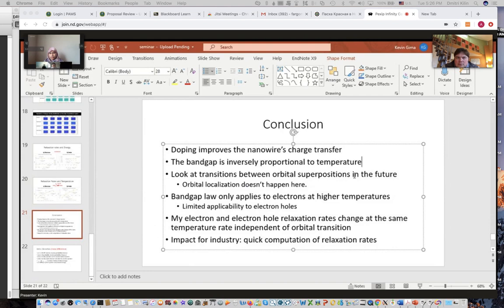All right. And then we find out that the band gap law only applies to electrons at higher temperatures. There seems to be a limited applicability to electron holes. And then my electron and my electron hole relaxation rates change at the same temperature rate, independent of orbital transition. So no matter what orbital transition you're looking at, the rate of change of my relaxation rate with respect to temperature is the same for all transitions.